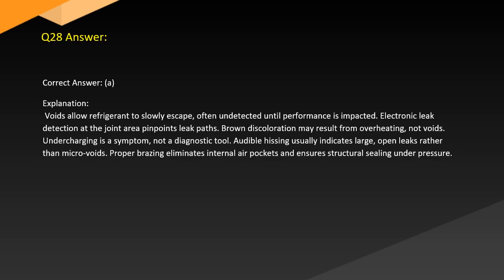Answer. Correct answer: A. Explanation. Voids allow refrigerant to slowly escape, often undetected until performance is impacted. Electronic leak detection at the joint area pinpoints leak paths. Brown discoloration may result from overheating, not voids. Undercharging is a symptom, not a diagnostic tool. Audible hissing usually indicates large, open leaks rather than microvoids. Proper brazing eliminates internal air pockets and ensures structural sealing under pressure.